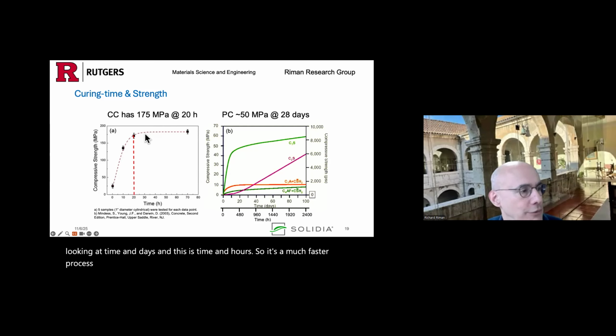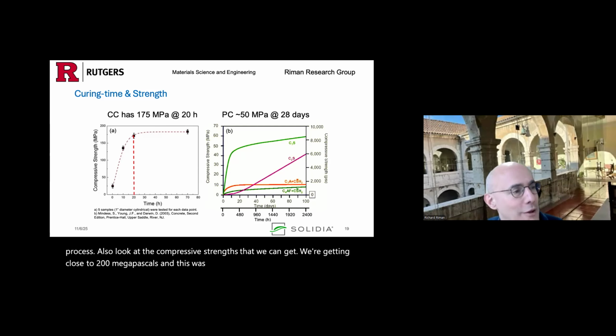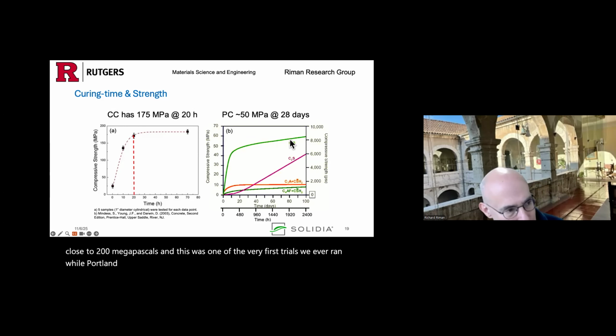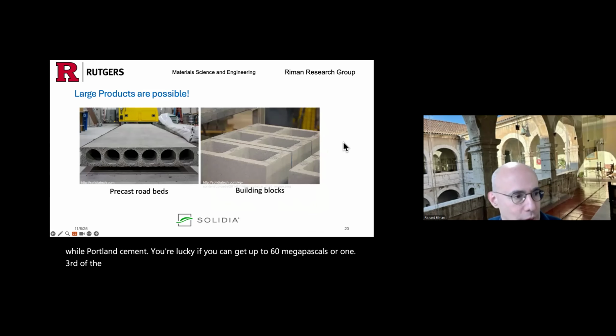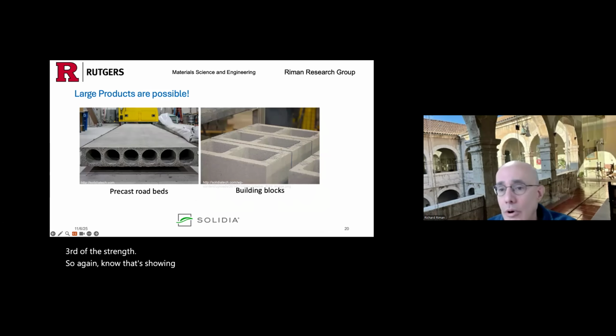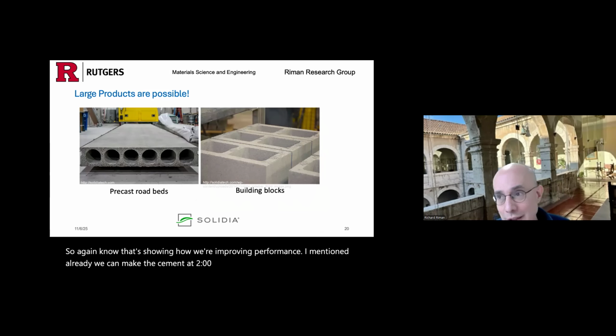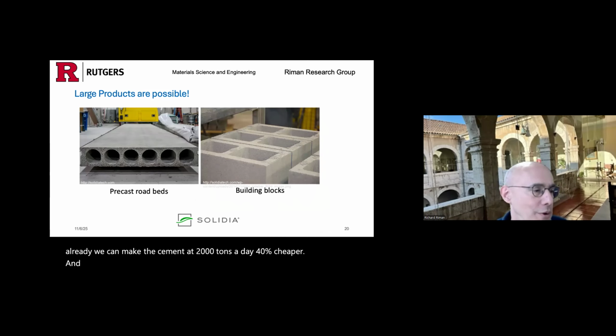Also, look at the compressive strengths that we can get. We're getting close to 200 megapascals, and this was one of the very first trials we ever ran. While Portland cement, you're lucky if you can get up to 60 megapascals or 1/3 of the strength. So again, that's showing how we're improving performance. I mentioned already we can make the cement at 2,000 tons a day, 40% cheaper.